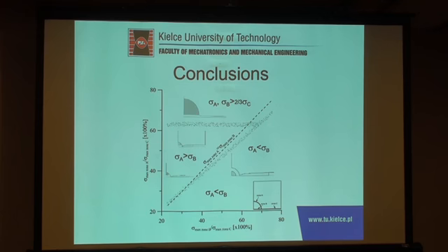If the stresses are lower, I mean this maximum stress for zones B and C are smaller, the first stage of damage is breaking of inclusion, and then debonding takes place. The area of debonding is greater for lower values of the stress. However, in any case, if the cohesive stress for zone A is smaller than cohesive stress for zone B, the first stage of damage is debonding.